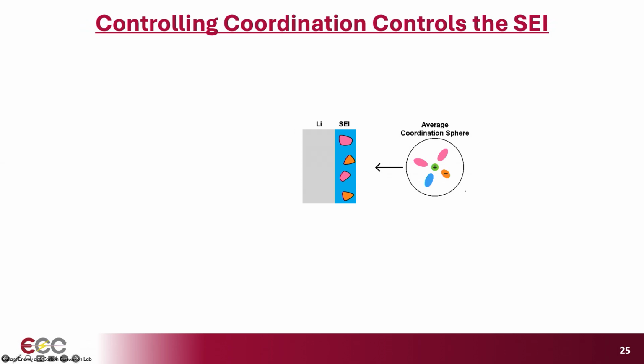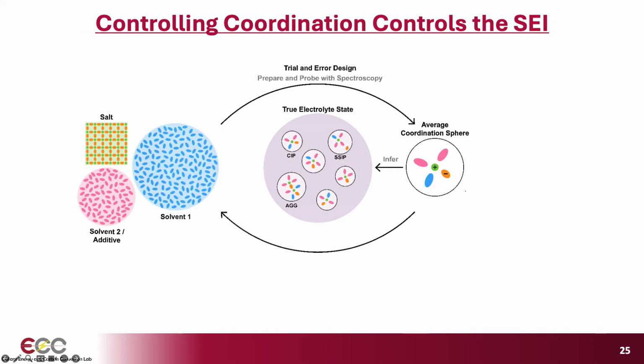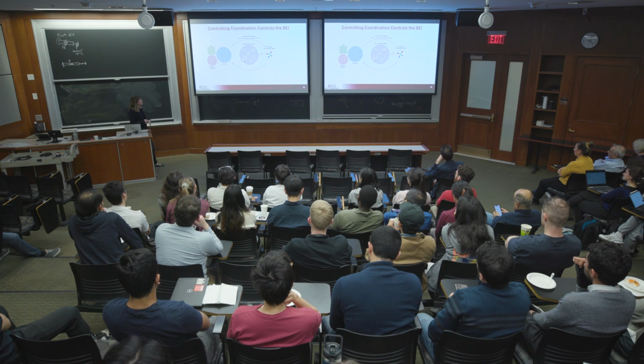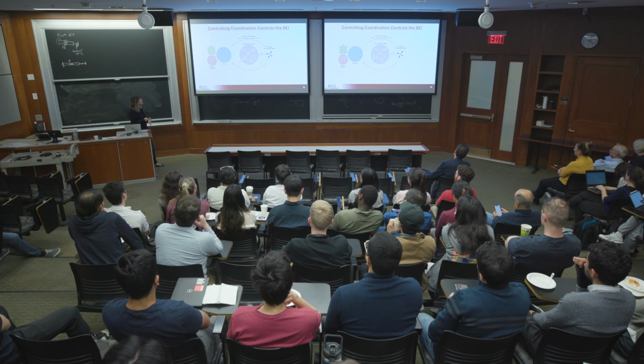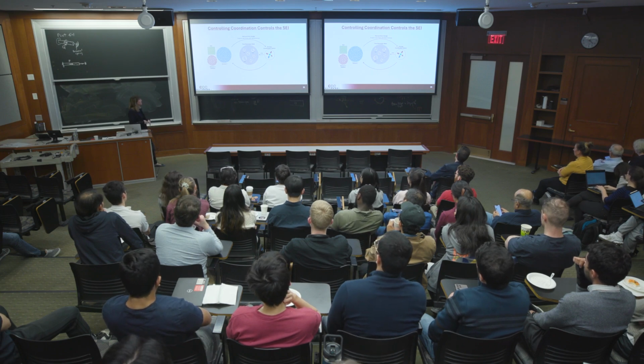SEI that we want. But this winds up being challenging because as experimentalists, we often don't have direct access or control over what the coordination sphere looks like. Instead, what we're able to do is kind of mix ingredients A, B, and C, perhaps we're aiming for a certain coordination environment. We take it to the lab, we characterize it, then we measure the performance. It may not be what we want, and then we kind of iterate laboriously through this process, which can take quite a lot of time to get the performance where we want it. And even then, maybe not precisely controlling this picture here.